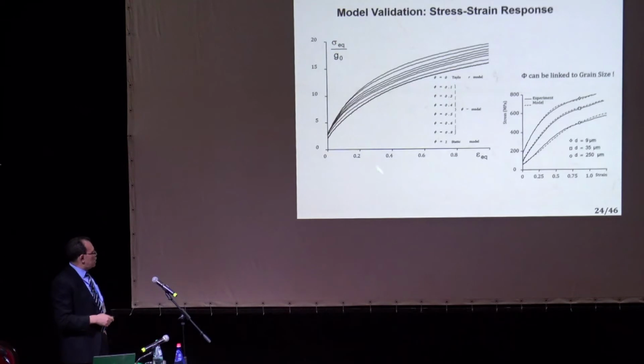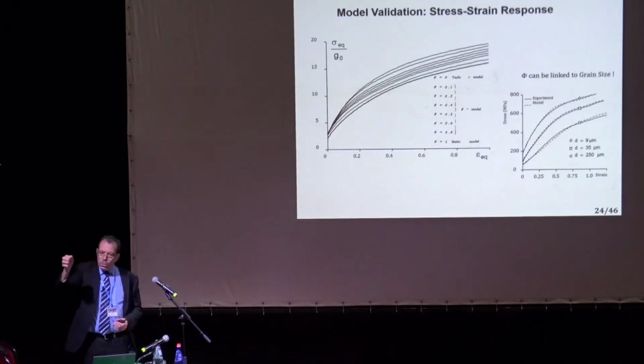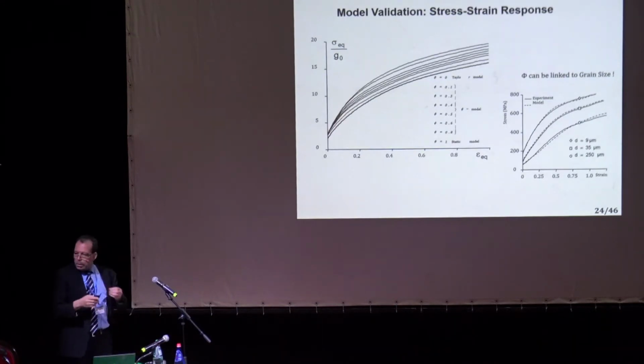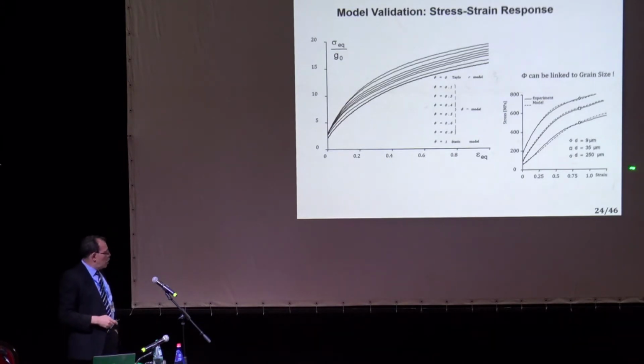This is the stress normalized versus the equivalent strain, and so it makes sense. This is logical to obtain. There is no surprise, and this shape here is dictated by the hardening law that we have imposed on the shear rates or the critical resolved shear stresses of different slip systems. Now, one thing we did also is we took a steel and we tried to fit the stress-strain curve, but for the steel with different grain sizes, okay? And so for these 3 different grain sizes, we chose different phis, okay? I forgot to put the phis here.